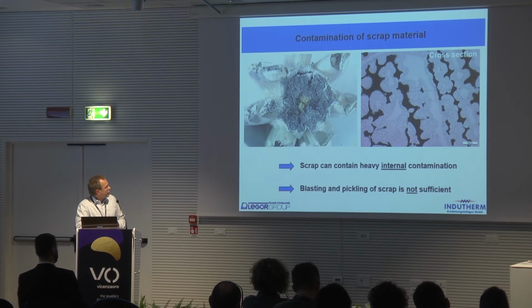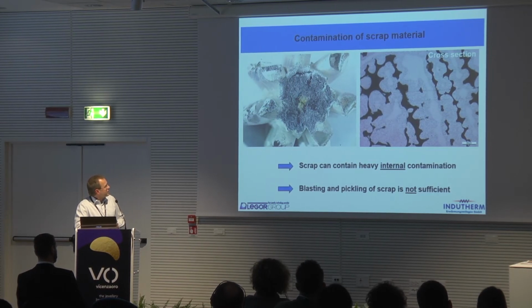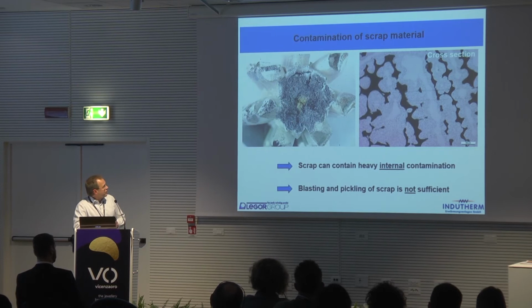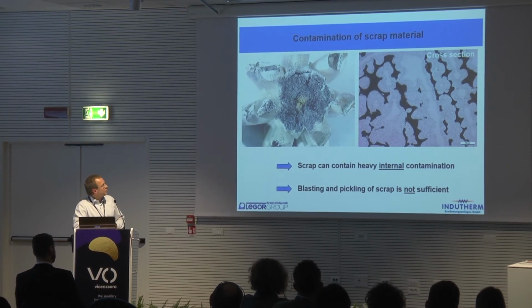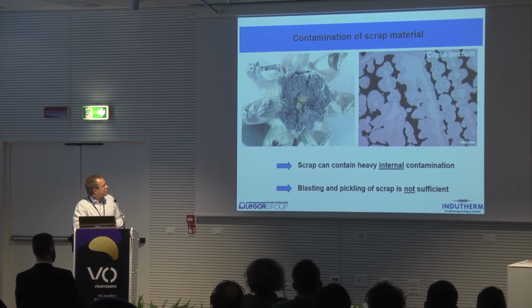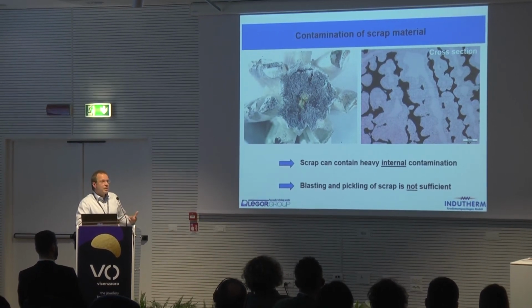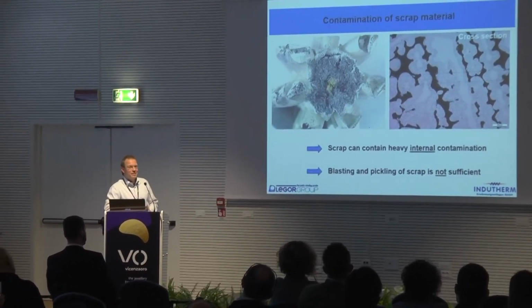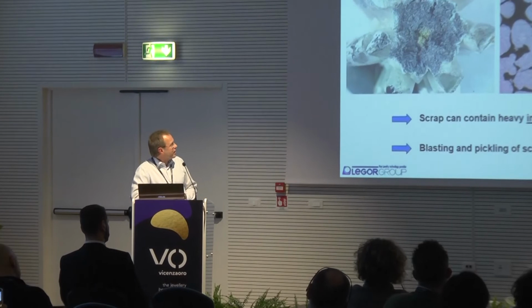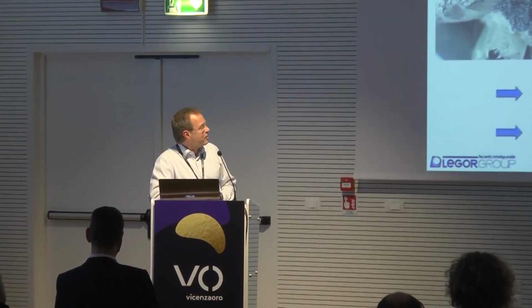Scrap material, I don't know if you can clearly see it on this photo here. This is a tree that has been pickled after casting, and where the as-cast items were chopped off here. So these are the remainders of the feed sprues, and the surface of the tree looks shiny because the tree has been pickled. But if we broke up the tree and looked inside the main sprue, you can still see a lot of contamination, dark colors here. So the pickle is not sufficient to clean the sprue after casting. It's an important step, but it's not enough to just pickle the tree or blast it.